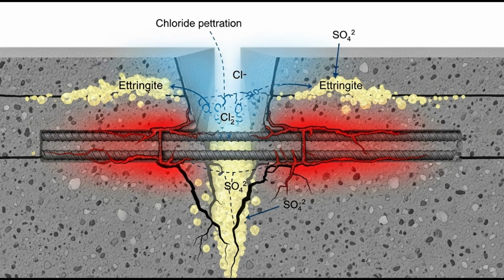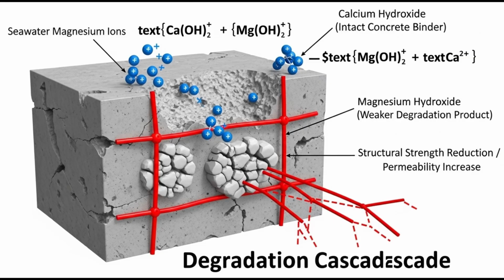Chloride ions penetrate, reach rebar, initiate corrosion. Sulfate in seawater reacts with calcium aluminate in cement. Forms ettringite, an expansive mineral, causes cracking. Magnesium in seawater reacts with calcium hydroxide. Forms magnesium hydroxide, weaker than the original compounds. All these reactions degrade the concrete, reduce strength, increase permeability, accelerate failure.